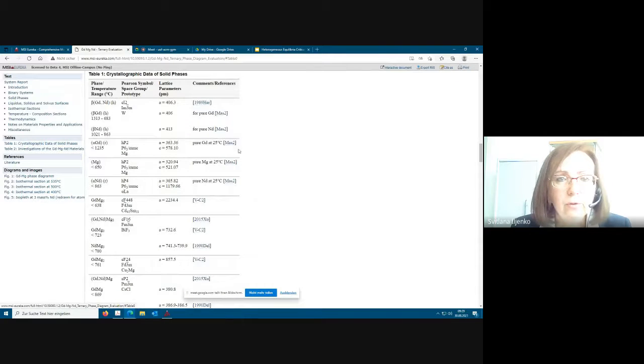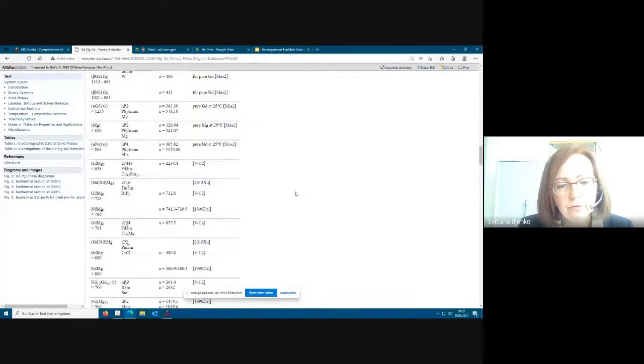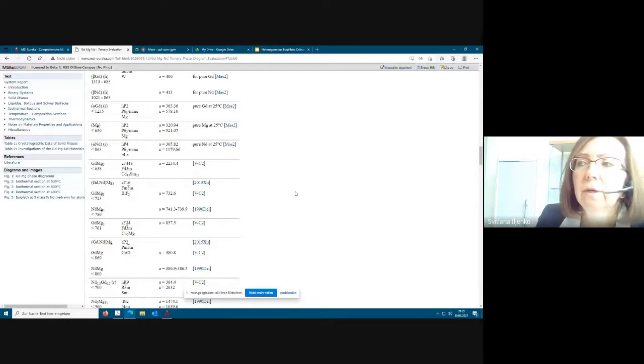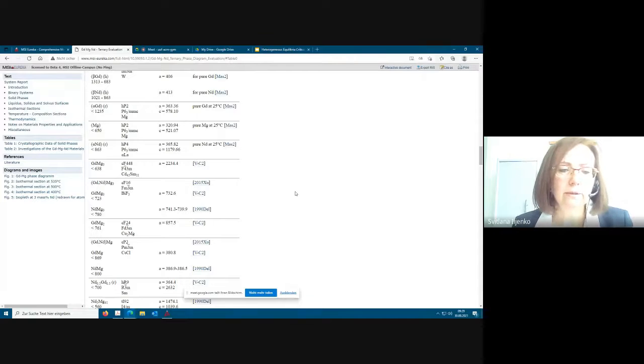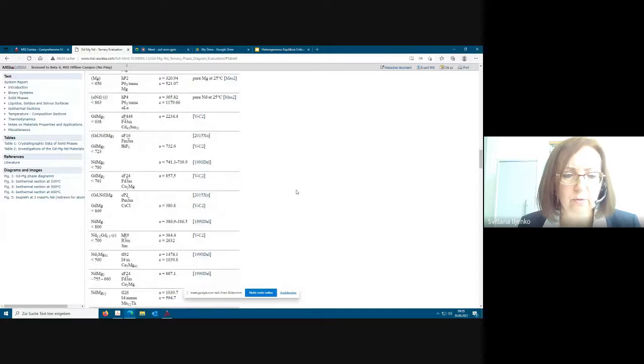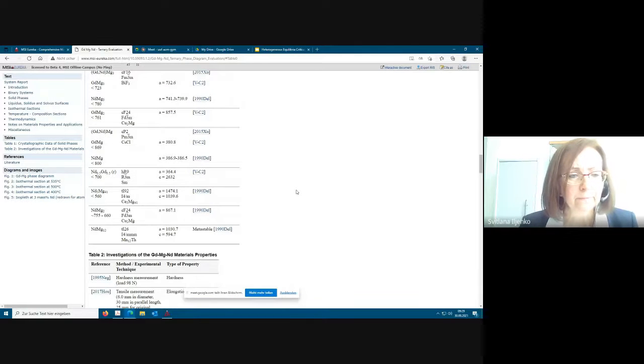And the table of crystallographic data reports only information about the stable phases which are existing. In the case of binary systems, there will also be binary metastable phases listed. In the case of ternary systems, ternary metastable phases are listed if they exist, but binary metastable phases are not listed. So this was one example.